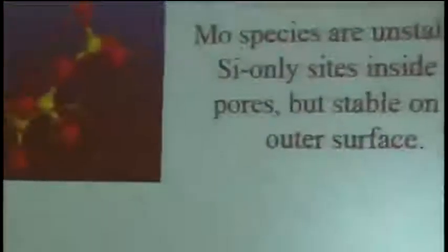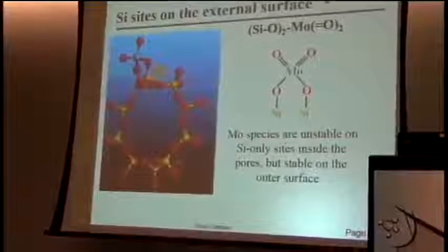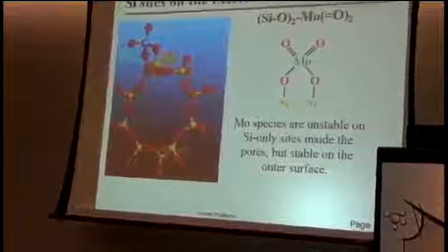We did additional calculation, we matched the frequency, and what we found from the calculations that we cannot stabilize those species in the pores of the zeolite, because we don't have the hydroxyls on silica unless we break the zeolite structure. But on the external surface of silica, we have plenty of hydroxyls. So those species must be on the external surface of the zeolite.